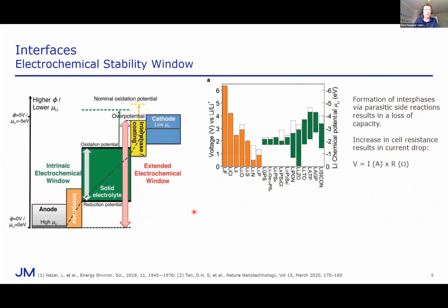So apart from conductivity, electrochemical and chemical stability is of primary importance. And the electrochemical stability of a solid state electrolyte is defined as the potential above which you get oxidation by the cathode material and the potential below which you get reduction by the anode material. And these green windows here can be extended in practice, because these are theoretical. These are extended in practice by overpotentials that may be associated with the actual oxidation reactions.